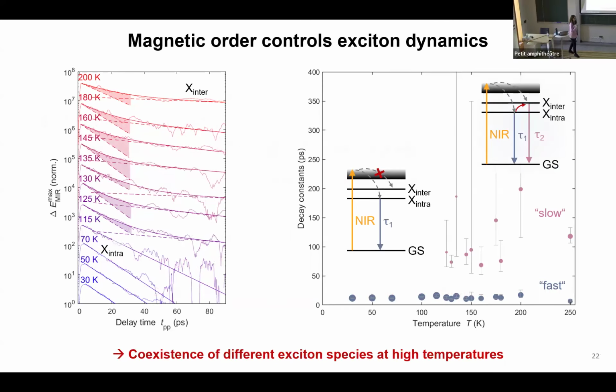So the take-home message of the first part would be that we learned that there is a coexistence of both interlayer and in-plane excitons above the Néel temperature, and that magnetic order is heavily influencing the ultrafast dynamics of our excitons, magnetic excitons in chromium sulfide bromide.